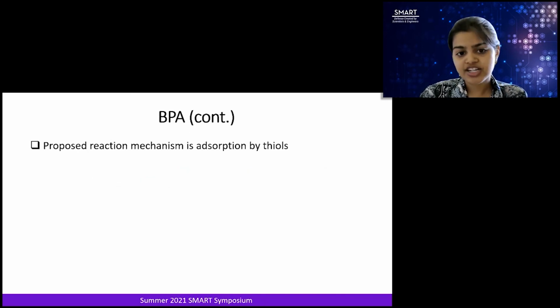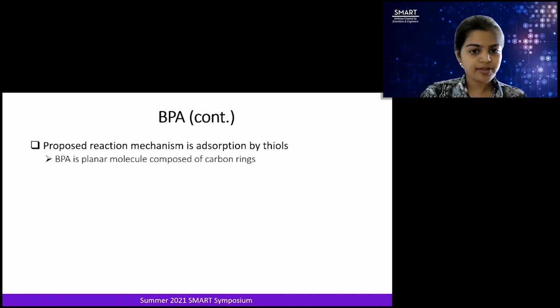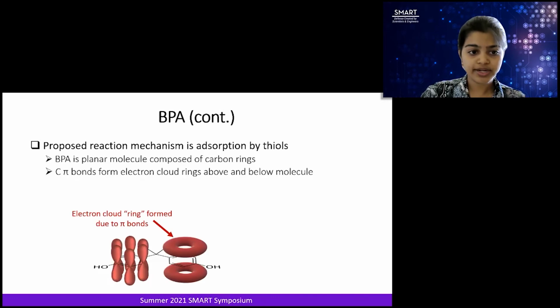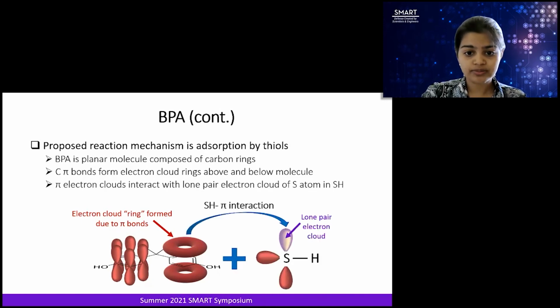Here, our proposed reaction mechanism is adsorption by thiols. BPA is a planar molecule composed of carbon rings. This allows for carbon pi bonds in the electron cloud rings above and below the molecule. Thiol-pi interactions would allow for the sequestration of BPA.